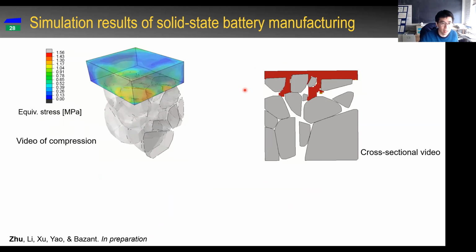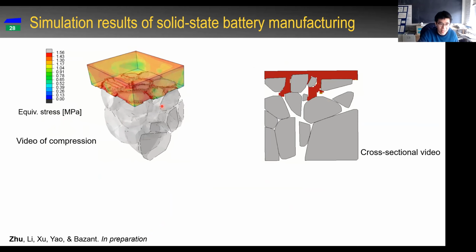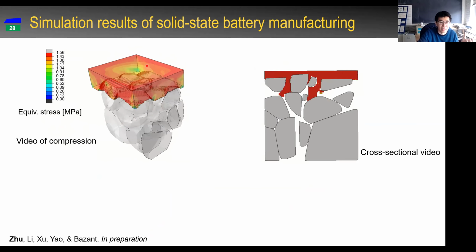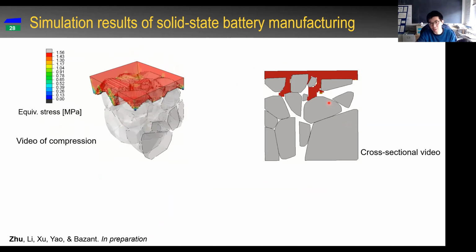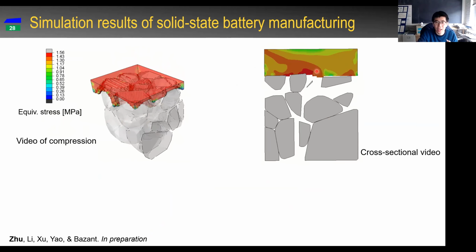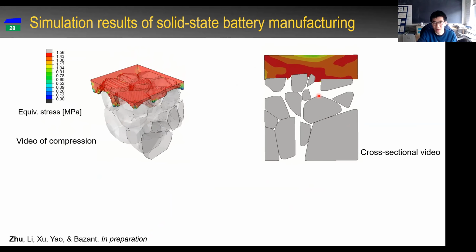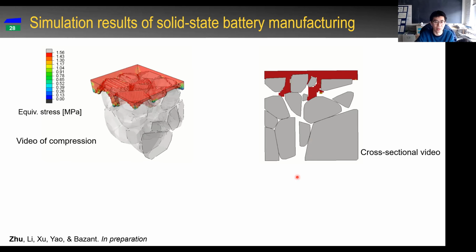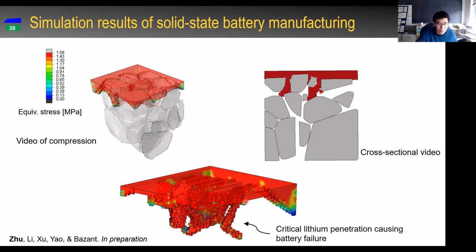Let me see. Okay, yeah. The video is now playing, and you can see the lithium being pushed into the solid electrolyte. And here is a cross-sectional video in which we can see the penetration. It's fine if it doesn't play. We can see clearly how lithium, like a fluid, goes into the solid electrolyte. This is what we learned from the creep and all the rate dependence. And here is the simulation result after we take the lithium plate out.